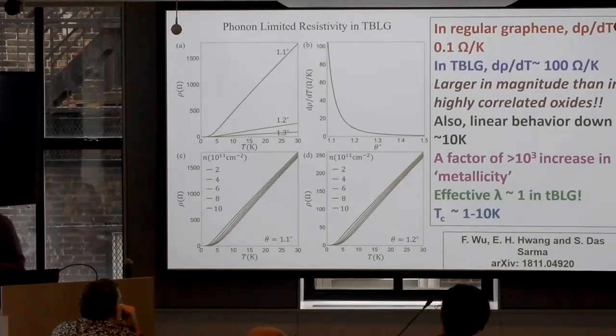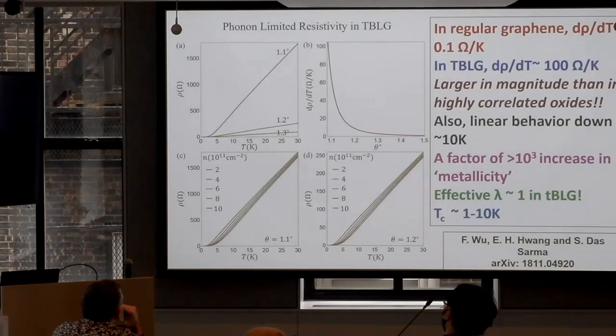Can you just comment or clarify why optical phonons are not important at all? You said high energy, optical phonon. Yeah. But there are many situations when the optical, I mean, not in BCS or not in Migdal, if the phonon energy is larger than the Fermi energy, but if it's lower, it doesn't have to be acoustic. Yeah. No, here we looked into it carefully, it just doesn't contribute. It's not like I discarded them without considering them. They come into play when I talk about untwisted structures. We include that, and sometimes that enhances TC slightly. Okay. So we have included them in some of the situations.